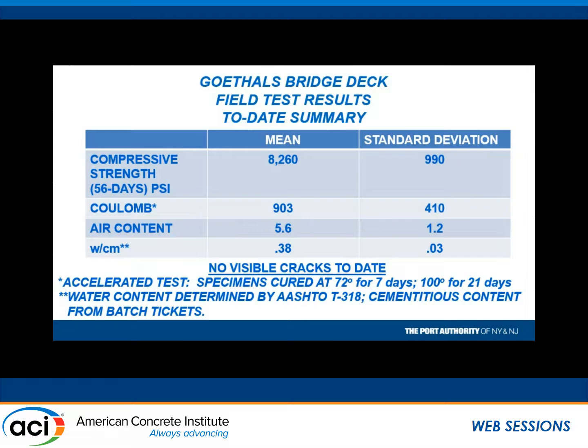You know, ASTM C94 used to say total water content should be within 3% of the design water. Do they still say that? If that was true, we would never do this test, okay? Because our life experience tells us it ain't that close. We're not doing this for the hell of it. We do this because when we first got this going, we were at 10% over or better in what water was in that truck. That's the reason why we do it.